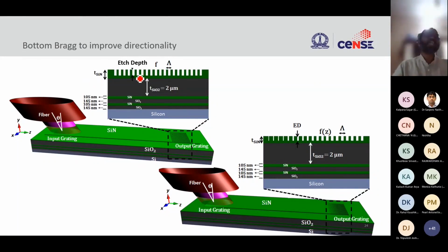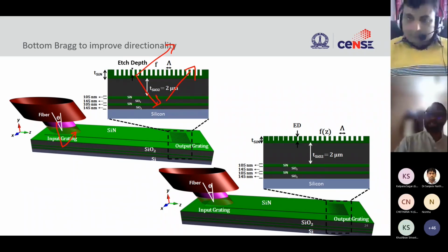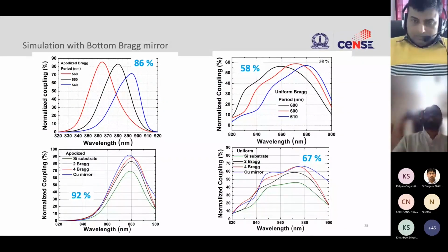As I told you, this is a grating, right? So the grating will diffract light in both the directions. So you have grating +1 and -1 order, let's say. So you will always have the symmetric diffraction. So the light that is going down can be reflected back. So I am recycling the light that is going down into the substrate, and then I can get it back by using bottom Bragg mirrors. Bragg mirrors are just simple alternate arrangements of silicon and silicon dioxide, which will act as a mirror. Okay, and this is something that we use for all the reflective coatings that we see in many places, and also anti-reflection coatings in many places. All right, so if we use that, now we can push this to 90%.